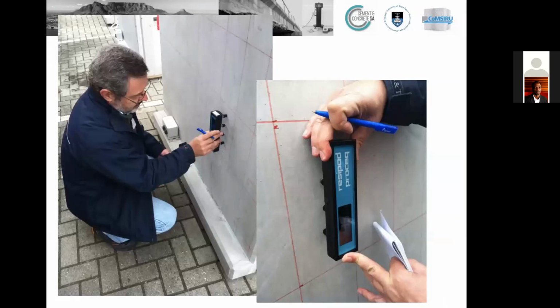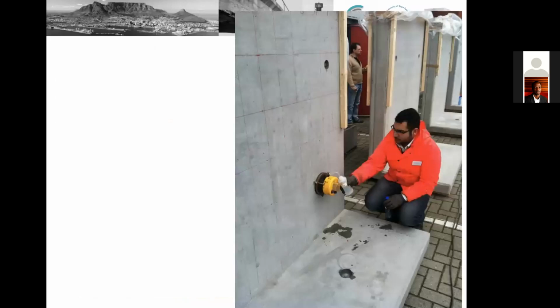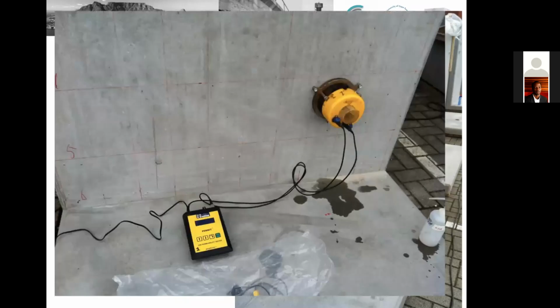Here you see resistivity being measured. We have a similar test. We measure chloride conductivity, again on lab-based samples. Resistivity is the inverse of conductivity, and this test method is largely used in Spain and South America to predict chloride ingress. Here you see a method from Northern Ireland, where you basically, in a localized spot on the surface, expose the concrete to an actual chloride solution to then measure how much of that chloride solution enters the concrete to determine the chloride ingress resistance of the concrete.